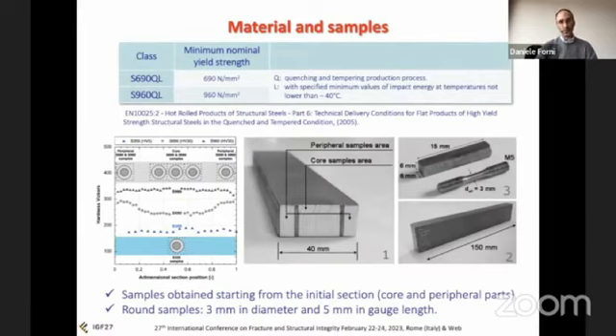But we know that the material is not homogeneous within its thickness, because we have a peripheral region which has a martensitic microstructure, while the core has a bainitic one. For this reason, we obtain two types of samples made of different submaterials from the core and the peripheral zone.